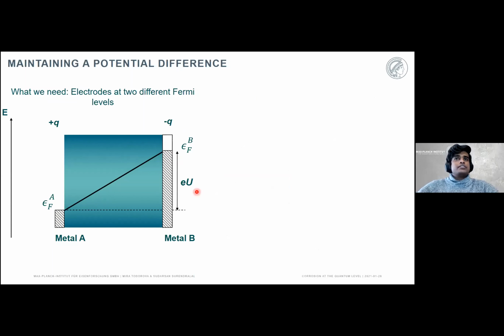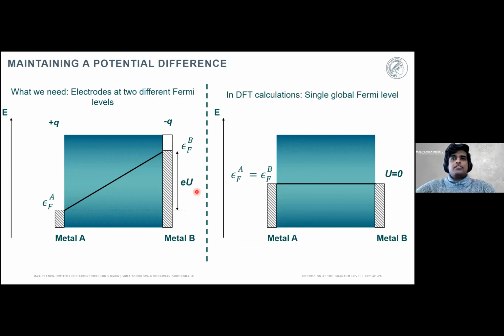However, density functional theory is a ground state method, always trying to get the electronic ground state. And as a consequence of obtaining this ground state, you can only have a single global Fermi level throughout the supercell. It means that even if you start with a situation like this, at the end of a DFT calculation, you would end up in a situation where both the metals would have the same Fermi level, and therefore you can't really have an electric field between two metals. This has been one of the biggest challenges in density functional theory modeling of such interfaces.